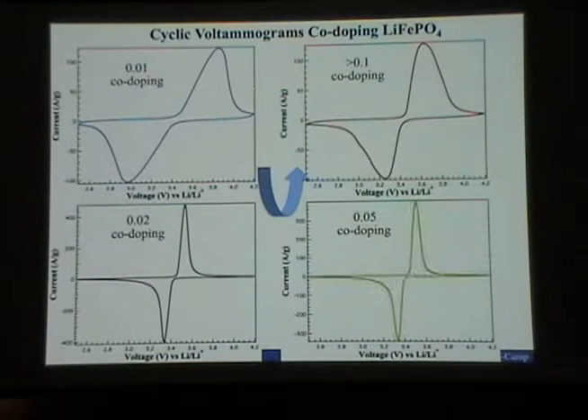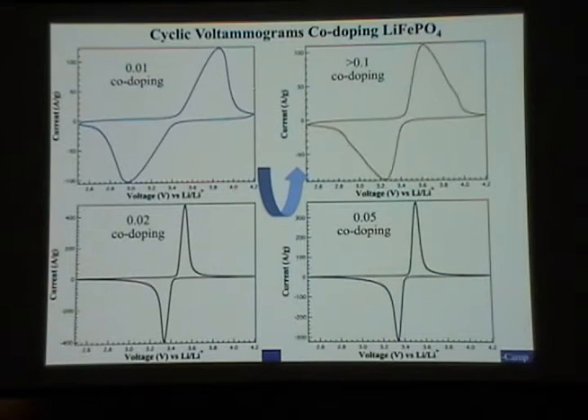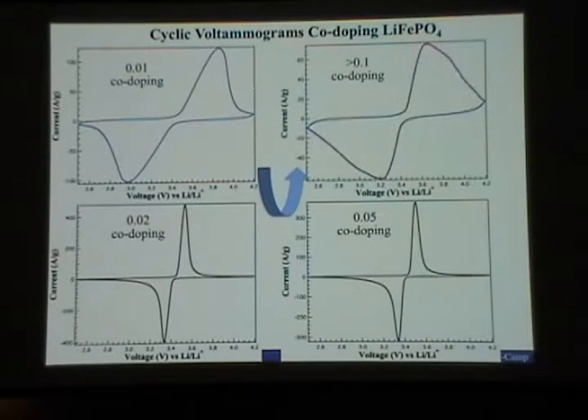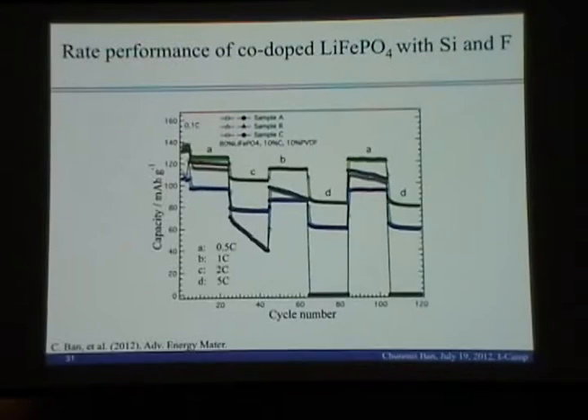And then we dope it even more, and it's still good. But if we dope at a very high level, actually they have impurities. A second phase comes in this part. So that means the doping level has a limitation, but we can say this doping does increase the performance of lithium iron phosphate. So this is just a comparison of different doping levels with lithium iron phosphate. And we found sample B has the best performance when we dope into the phosphate